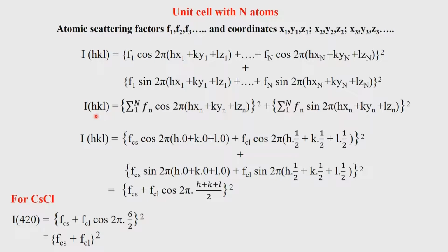See here, how did we solve the phase problem in calculating the intensities? We solved the phase problem by looking at the fact that, depending upon where these atoms are, the variation is with respect to 2 pi times Hx plus Ky plus Lz. So, that gave us the phase. This is because we know where x, y, z is. Since we do not know where x, y, z is, the modulus value which we get for the structure factor is devoid of phases. No experimental way is available with the way we do the experiment. No experimental approach can be developed to find the phase. So, therefore, we have to determine the phases or guess the phases that are associated with the structure factors.